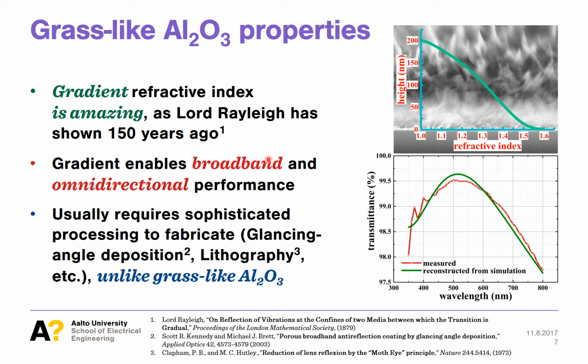Gradient refractive index enables smooth transmission of light because there is no sharp refractive index contrast, which causes Fresnel reflection. Gradient anti-reflective coatings have great broadband and omnidirectional performance. Unfortunately, creating a gradient refractive index profile usually is a challenging task and requires sophisticated techniques, though the obtained performances, for example, multi-layered glancing angle deposited coatings, are excellent. Grass-like alumina fabrication, in contrast, is not a complicated process, as you just saw, and does not require a multi-layered deposition. The refractive index gradient forms there naturally.